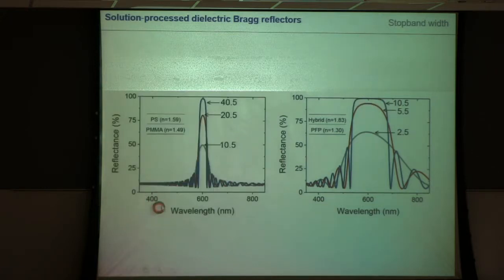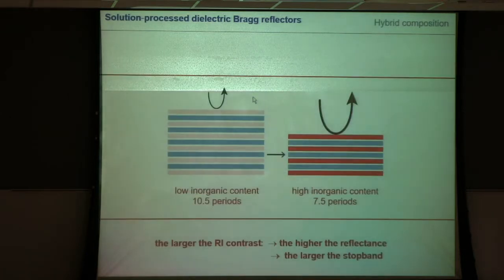In case you use a very small refractive index, here just simple polystyrene, again plexiglass, you get a very narrow stop band. Important, for instance, in car applications where they want to look at the driver with near infrared, but they don't want to interfere with any other of the light that the driver sees. But you see the issue is the narrower your stop band you want to get, the more layers, the more periods you need. So there's a compromise, and you really have to decide what is best for your application.